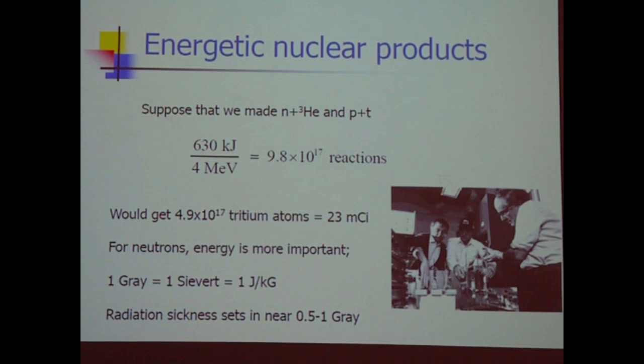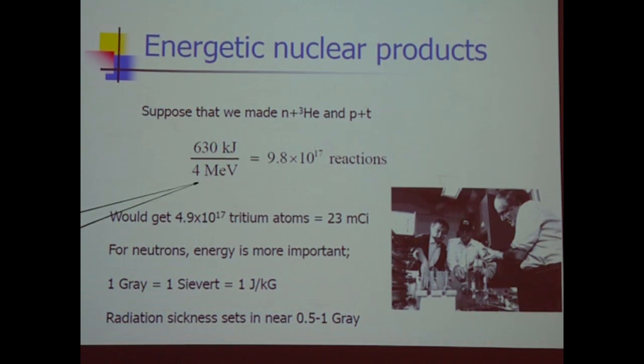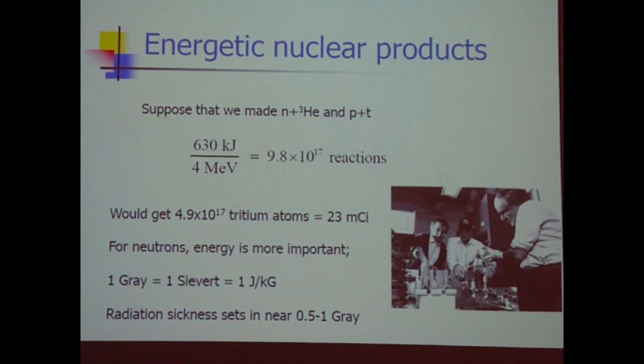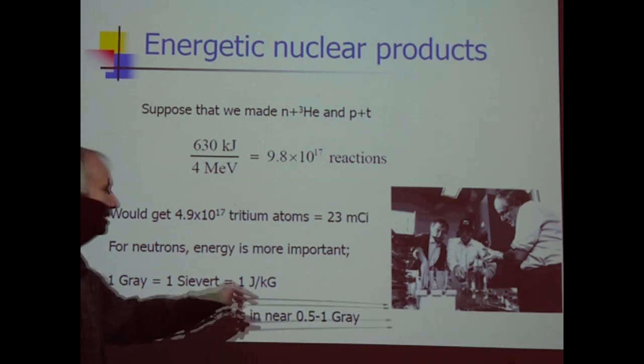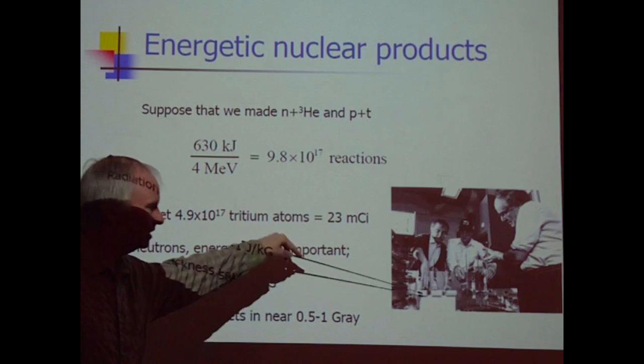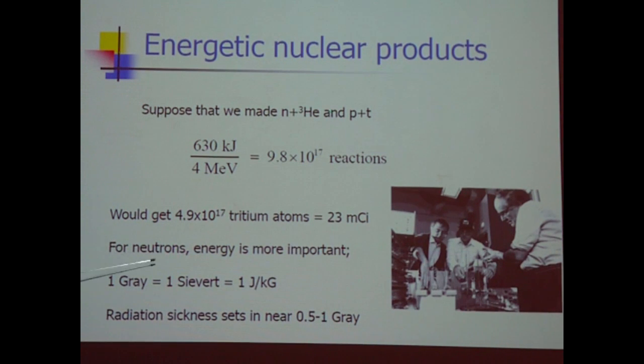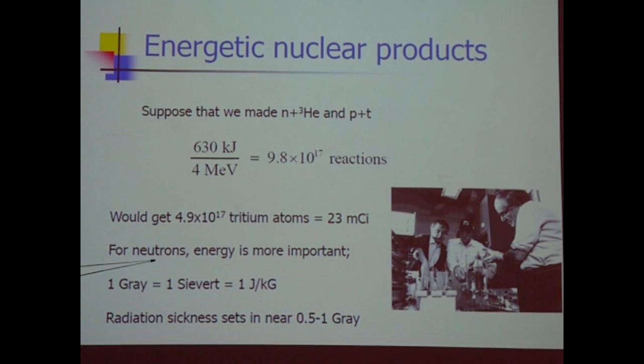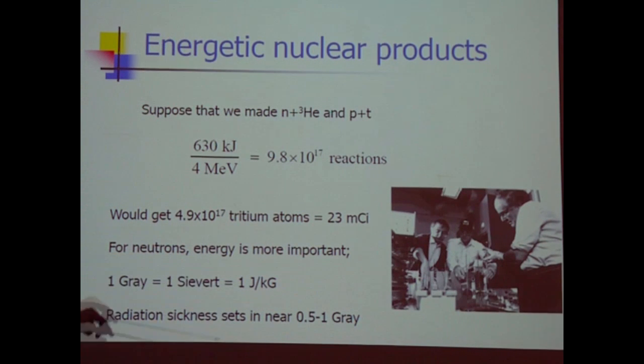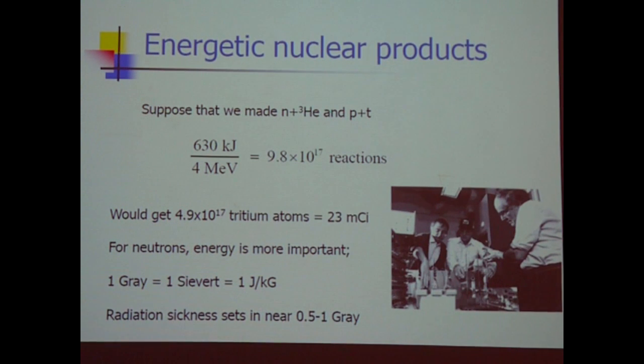So that motivated Fleischmann to conjecture that we're seeing energy of nuclear origin. Now, suppose we had DD fusion making neutron plus helium-3 or proton plus triton. So 630 kilojoules over, call it, 4 MeV. We get this many reactions. The question is, would we be able to see that? As I pointed out before, here's the Fleischmann-Pons experiment and the cell, and there's no lead shielding. It turns out that for neutrons, the kinetic energy is important. One gray is one sievert, which is 1 joule per kilogram of irradiation. So if you were getting a watt's worth of neutrons coming off and you're standing close to it, you're going to get very serious medical problems in a relatively short time of exposure to such a high level.